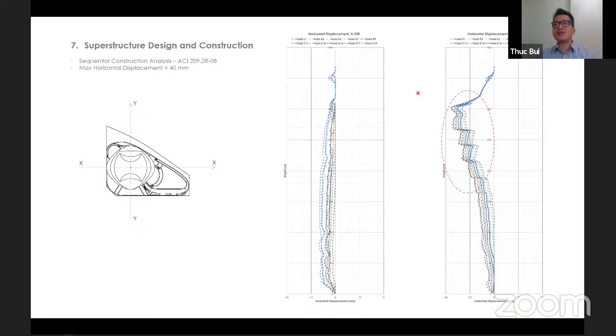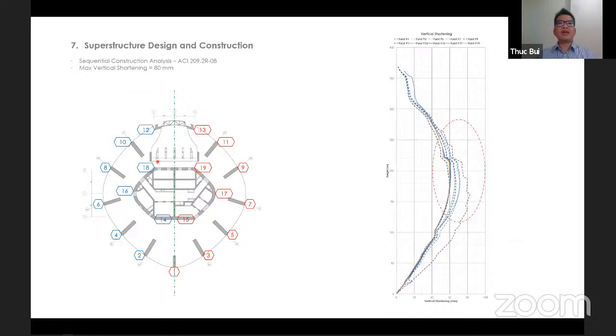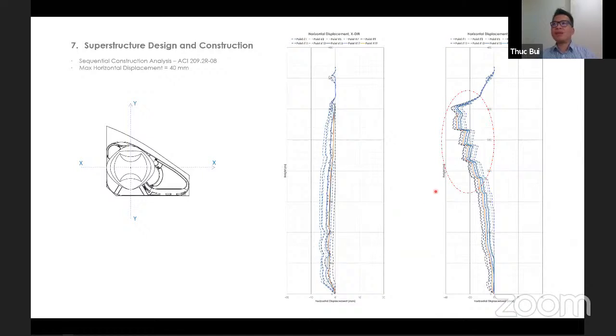However, it is critical in Y direction, because if you look at the floor plate, we have a 300 meter tall atrium here on the north side of the floor plate. So the center of mass tends to be close to the south side, and the tower will be moving in Y direction around 40 to 50 millimeters. This movement will be compensated by adjusting the jump form and providing horizontal cambering for those floors.